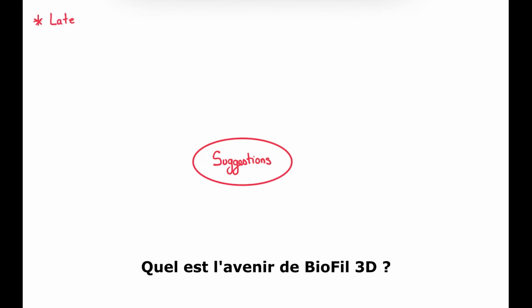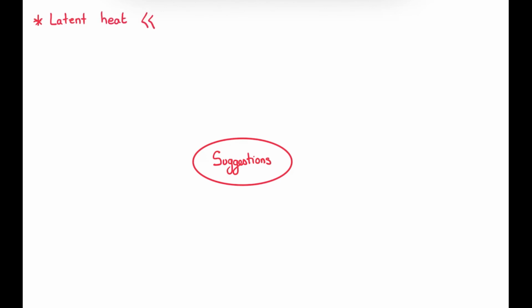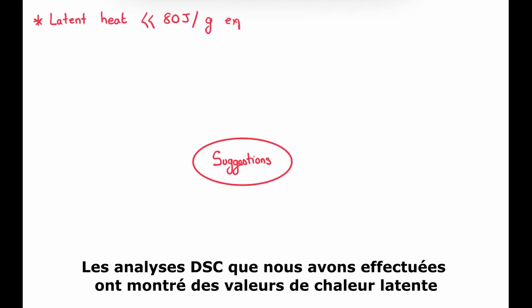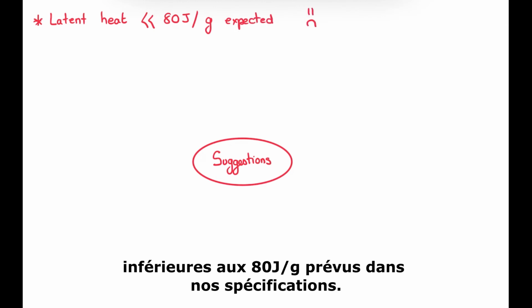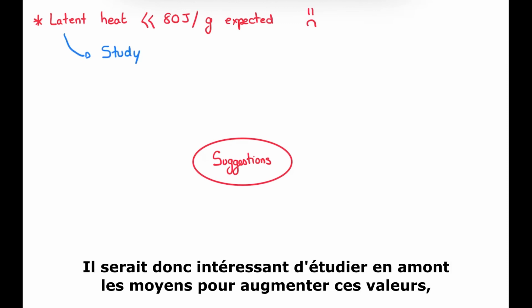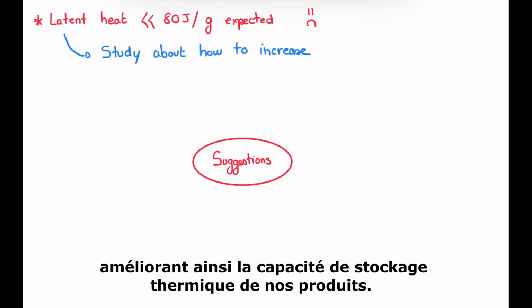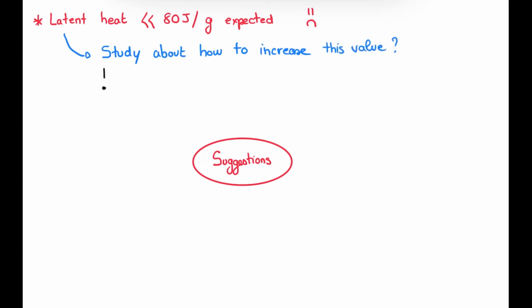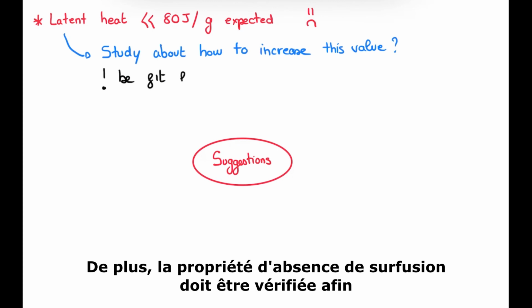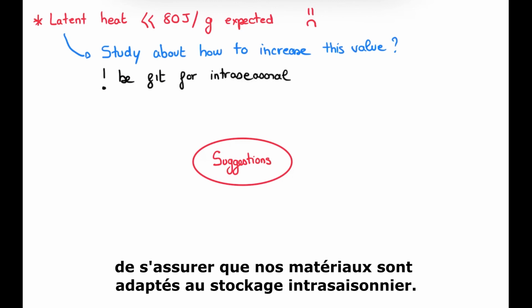What about the future of BioFil3D? The DSC analysis that we executed showed latent heat values lower than the 80 joules per gram expected in our specifications. It would thus be interesting to further study ways of increasing these values, consequently improving the thermal storage capacity of our products. In addition, the no supercooling property should be further verified to be sure our materials are fit for intra-seasonal storage.